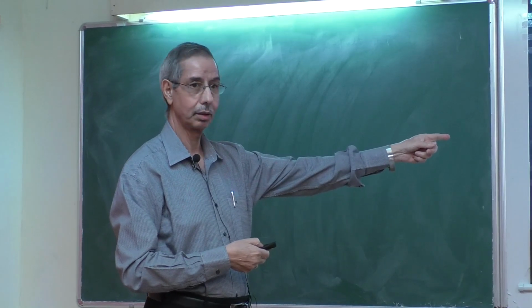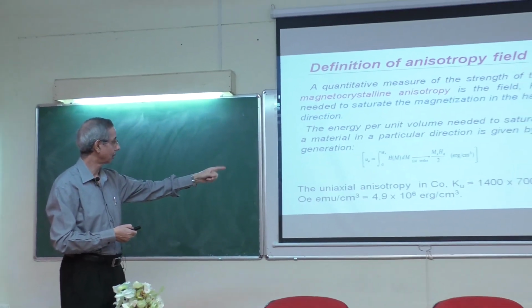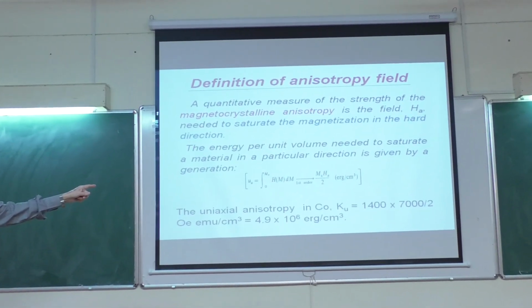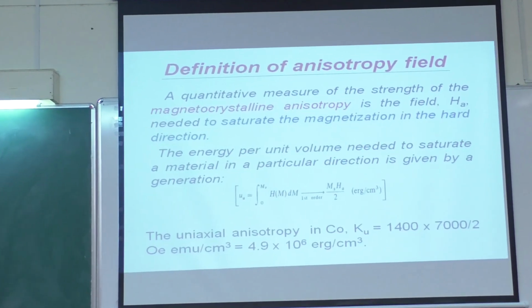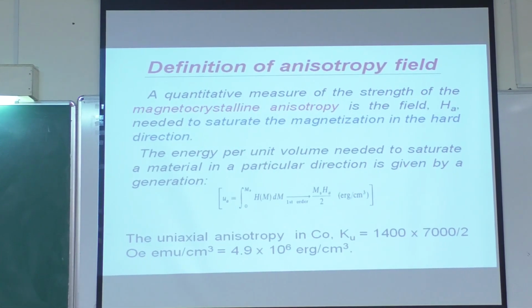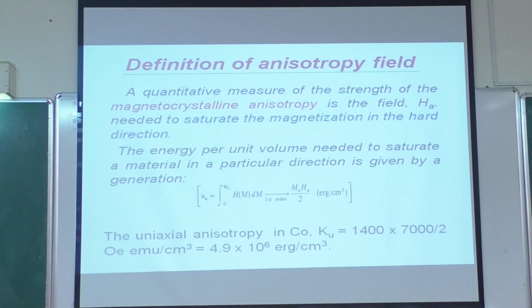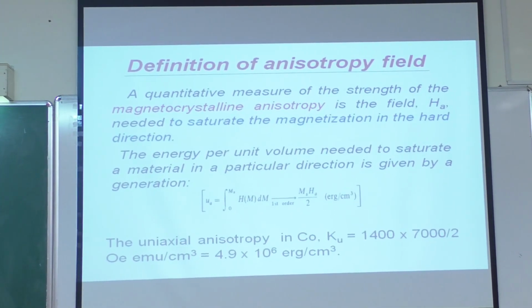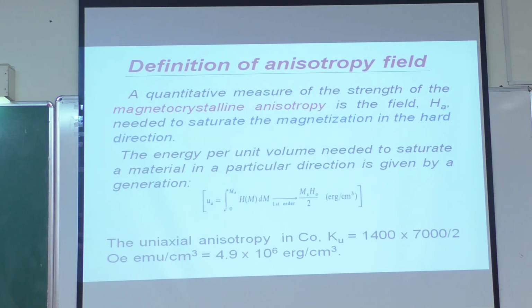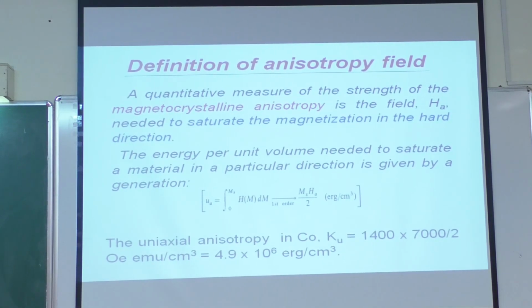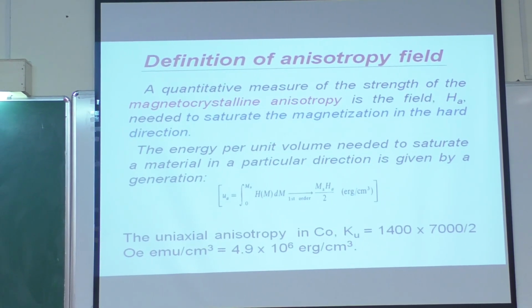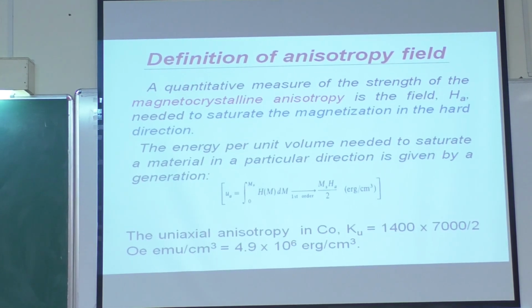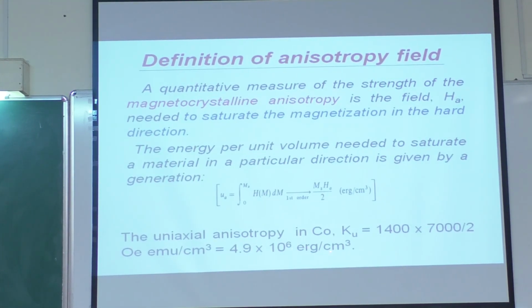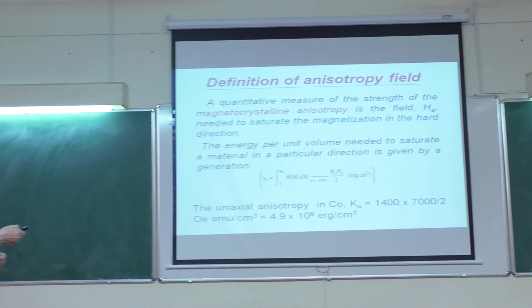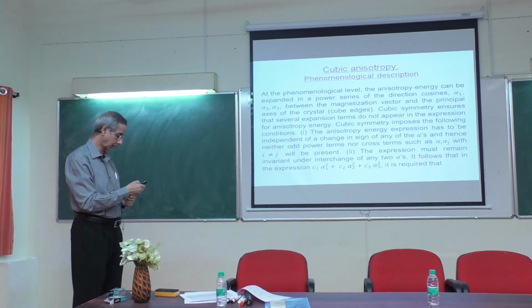And this is the anisotropy field that you will have to apply to be able to get the magnetization out of the easy axis along the field axis, where it saturates finally. So uniaxial anisotropy in cobalt is very high. It's of the order of 4.9 × 10^6 erg per cc. This is just to give you some idea.